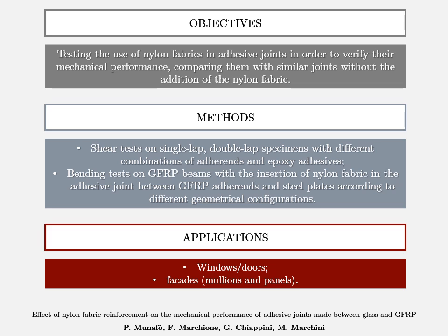These aims are investigated by shear tests on single lap and double lap adhesive joints using different combinations of adherends and epoxy adhesives, and bending tests on GFRP beams with insertion of the nylon fabric in the adhesive joint between GFRP adherends and steel plates according to different geometric combinations.